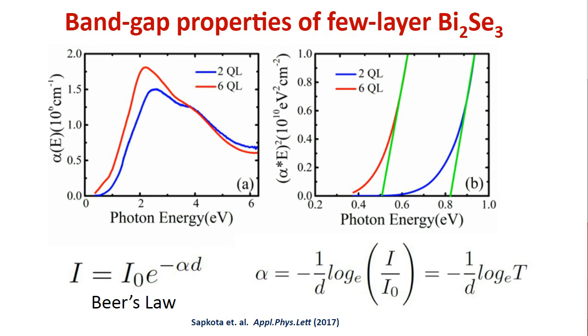And we can go ahead and analyze the optical band gap using the direct gap analysis. Sometimes these are called the Tauc plot. And again, this is straight up Beer's law, right? So we are doing an absorption analysis using the transmittance data and knowing the thickness. The thicknesses were calibrated using the X-ray reflectivity method. Again, you can clearly see that the optical band gap of a 6 quintuple layer sample is about 0.5 eV, whereas the band gap of a 2 quintuple layer is about 0.8 eV. So that's the inference from here.